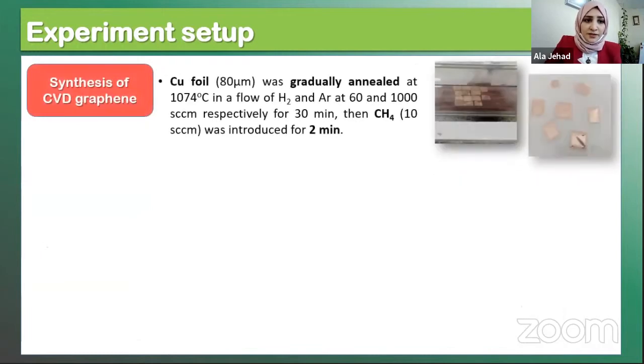For the synthesis of graphene, we synthesize monolayer graphene with the assistance of copper foil, gradually annealed at 1074 with the flow of hydrogen and argon. And then after the annealing process, we open methane gas for 2 minutes.